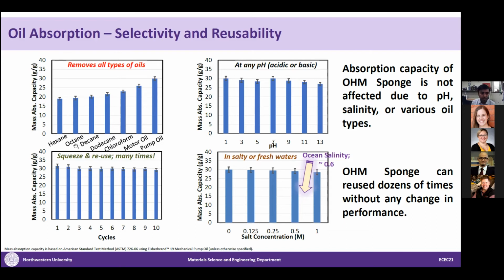The bottom plot is the reusability plot, where we have squeezed it and reused it again. And what we have seen is, even dozens of times, it doesn't change any capacity. Here we have shown it for 10 times. You can see the absorption capacity does not change, almost stays close to 30.